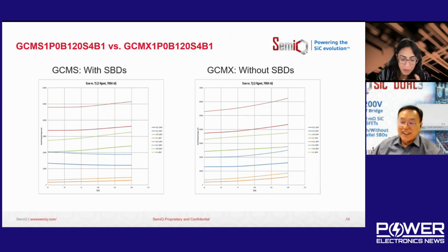I was curious because you said that you test at 1450 volts for the 1200 volt devices. What about the newer 1700 volt devices? How are they being tested? For the 1700 volt device, the gate oxide burn-in process is exactly the same. There's no difference. We also apply it to 2.3 kV, but the drain burn-in is still challenging for higher voltage. So we are working to improve that drain-source burn-in process at high temperature. But room temperature testing at the 1 milliampere leakage level, around 2.2 kV, 2.3 kV, is not an issue. So it's in process.